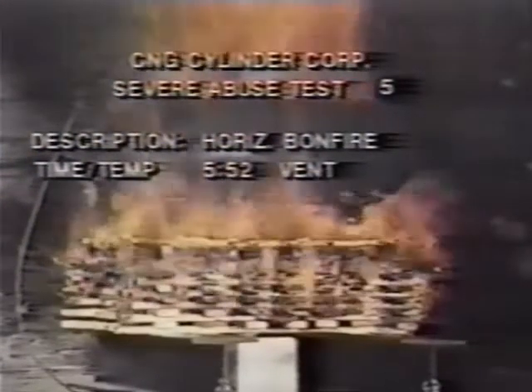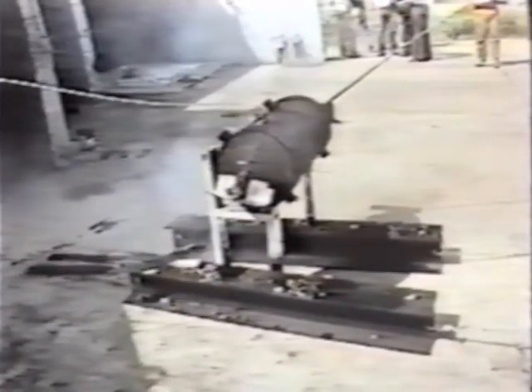The pressure relief device vents at this point. Amazingly, the natural gas does not ignite, even though a rubber gasket on the bracket mount does catch fire. The ignition temperature of natural gas is 600 degrees higher than that of gasoline. The half-full fuel tank is a special problem solved by the CNG Cylinder Corporation's double redundant safety design. The burst threshold at half-full changes, creating the need for heat-sensitive as well as pressure release valves. These valves operate at 3,775 psi at a temperature of 212 degrees. As is seen here, the new CNG cylinders survive the test without the possibility of bursting, and the gas itself never ignites.